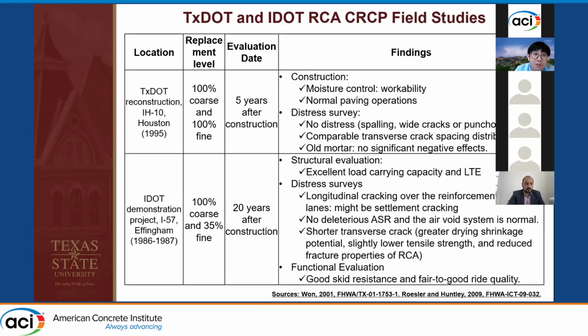And we also have RCA CRCP studies which were reported before. For example, TxDOT had existing RCA CRCP studies. So in 1995, TxDOT reconstructed IH-10 in Houston, and they used 100% coarse RCA and 100% fine RCA to replace coarse aggregate and fine aggregate respectively. And after 5 years of construction, Dr. Mu Wang from Texas Tech University visited the